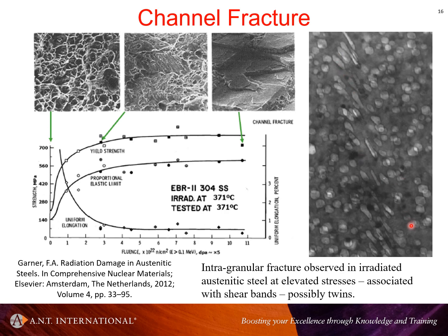But because they saw this shearing, and that's a separate issue, whether the shearing is from twinning or from some other mechanism, irrespective of that, there was a link made then, this must relate eventually to a crack formation, and that leads to transgranular cracking, as we see here. I think also in one of Frank's publications, he believed that the depletion of nickel in some areas will result in the formation of a martensite phase, which again is total speculation.